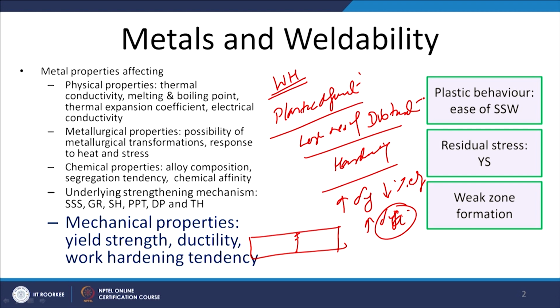Like say this is the joint interface produced after the plastic deformation based approach of the joining. So, hardness distribution will be showing a significant increase in hardness as compared to the other areas at interface. This kind of behavior is observed by those metals which show good work hardening tendency. Then the reverse is also possible, like those precipitation hardenable or those strengthened using the grain refinement, and work hardening behavior is very limited. In that case, even the softening of such kind of the zones can also take place, which are subjected to the severe plastic deformation, and in that case we will find the low hardness zones, especially at the weld interface or in the heat affected zone due to the development of the heat. So, this will be leading to the softening, and in the case when the material is showing the good work hardening tendency, it will be leading to the hardening.